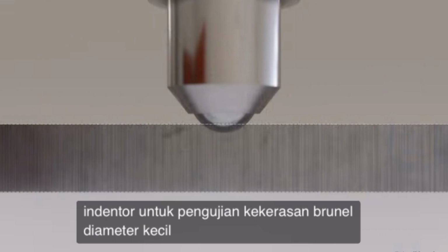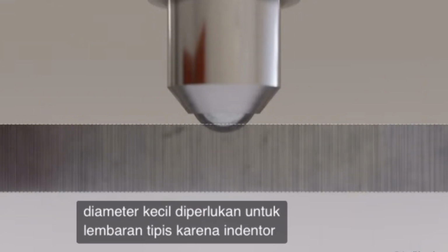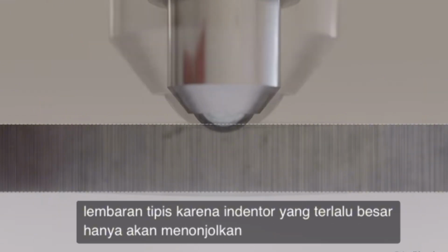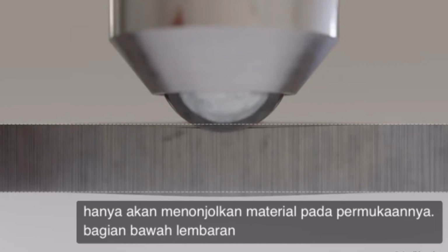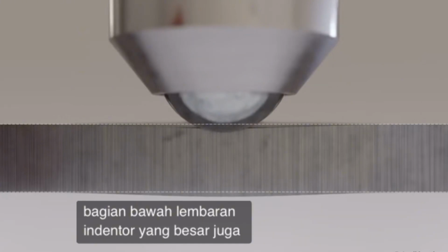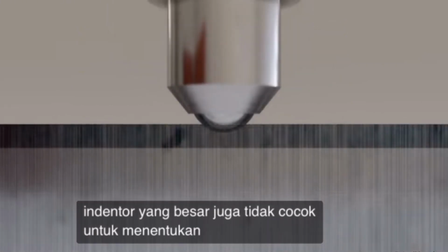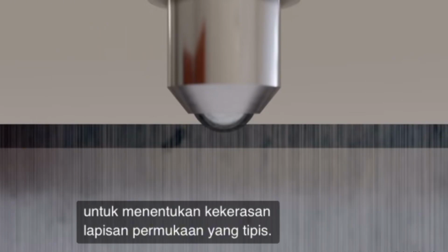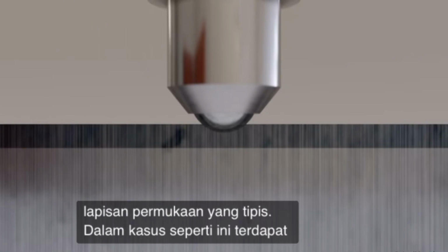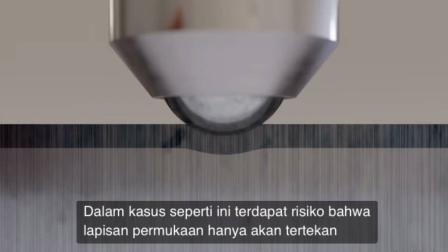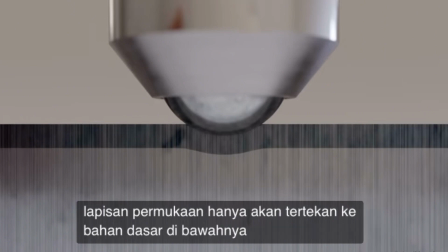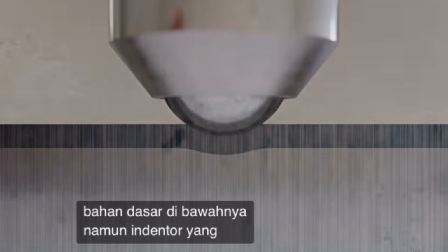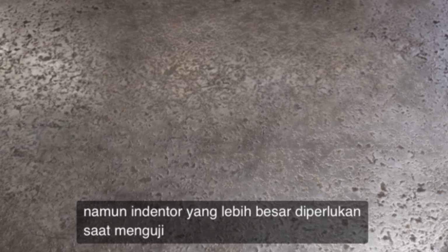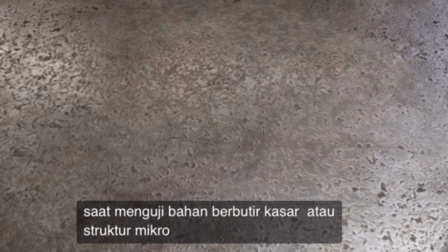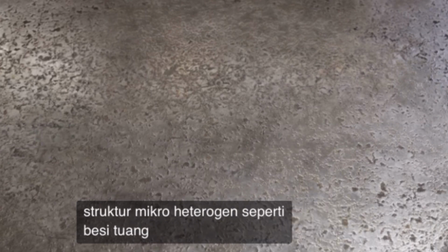Small diameters are necessary for thin sheets, as indenters that are too large would only bulge out the material on the bottom side of the sheet. Large indenters are also not suitable for determining the hardness of thin surface layers. In such cases, there is a risk that the surface layer will only be pressed into the underlying base material. However, larger indenters are required when testing coarse-grained materials or heterogeneous microstructures, such as cast iron.